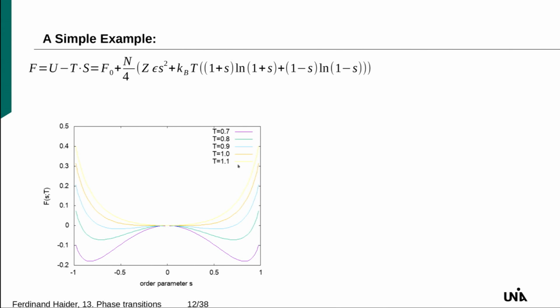So this is very nice, I think. You see here, at the temperature above the critical temperature, there is one single minimum here. If you approach the critical temperature, the curve becomes flatter. That's at the critical temperature. Below the critical temperature, this converts to a maximum, and you get these minima here and here at plus minus.